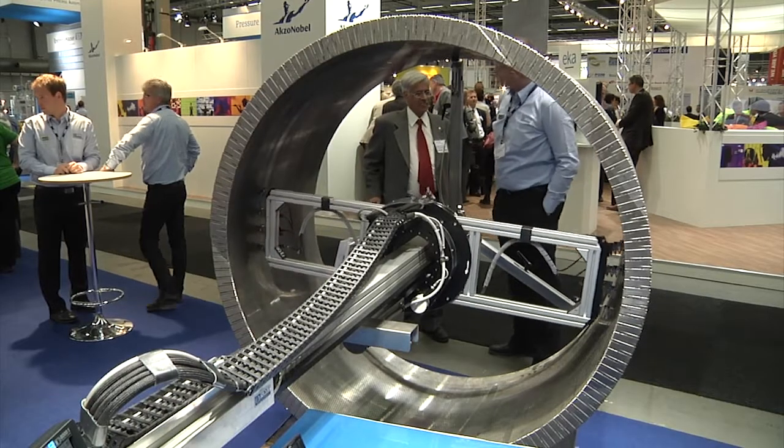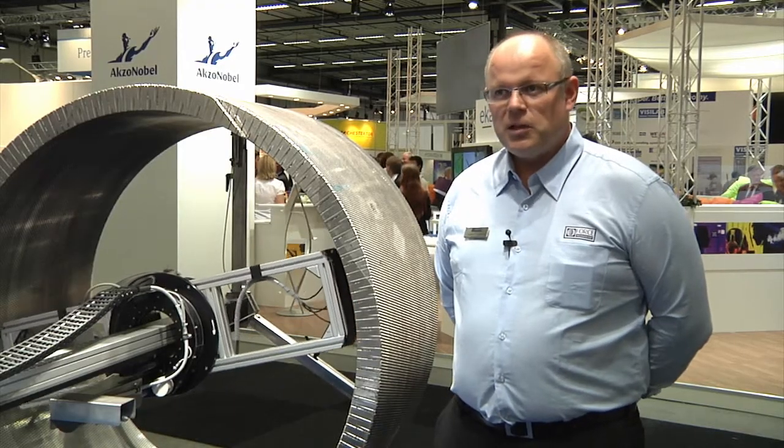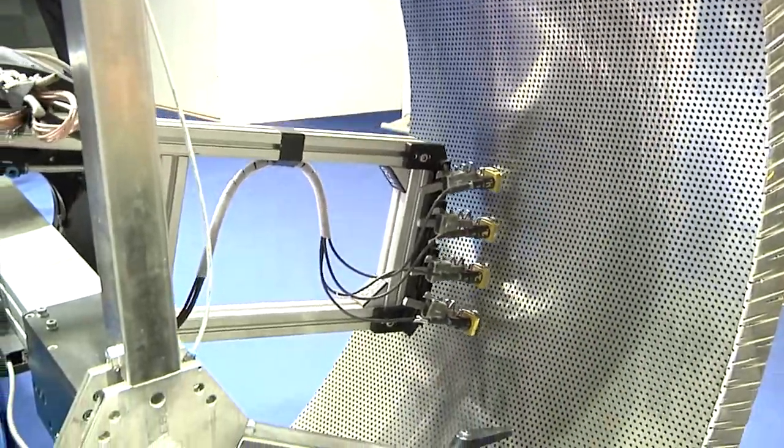This machine has a high detectability of cracks that are very tight. Compressed cracks are a problem when using liquid penetrant testing — it is not certain that the cracks are indicated by penetrant testing.